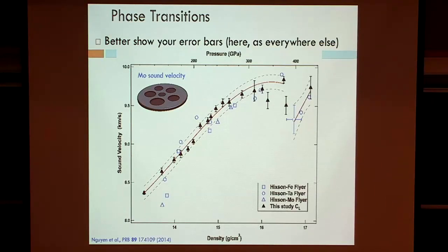Paul, how confident are you that the temperature field in the shock-loaded front is homogeneous? That is, in a world in which we used to worry a lot about shear bands and so forth under shock loading, and especially as I look at that curve with what looks like incipient melting before that big discontinuity in your highest pressure point that might be in the solid field, what's your current sense on how homogeneous the temperature field is? So I think shear bands are a phenomenon that you're mostly going to encounter close to the Hugoniot elastic limit, where some of the material is failing and some of it isn't. Right? We're way above that. So I think that particular instability is not an issue. There may be other instabilities. And it would be nice to do imaging experiments where we see that directly, which we haven't done yet.